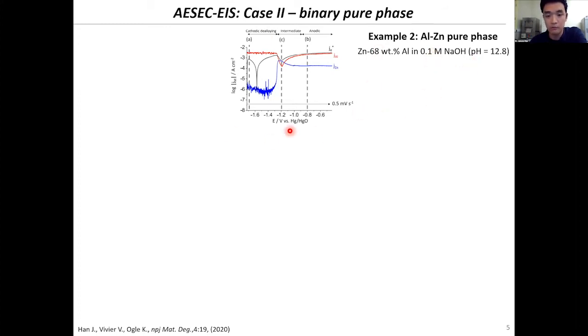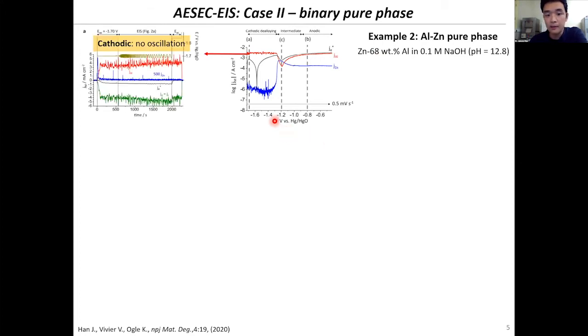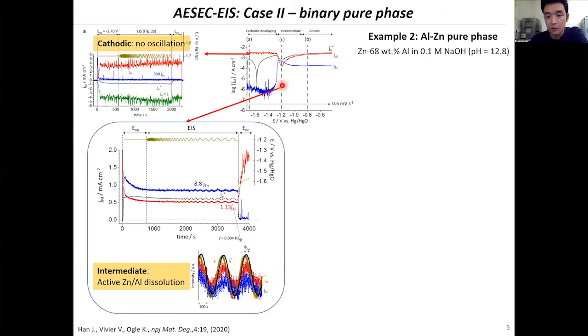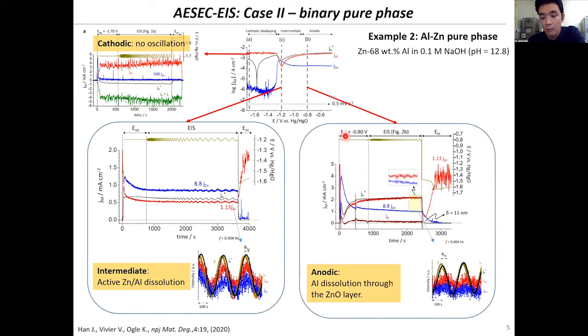So this is the polarization curve of this pure phase at pH near 13. And in the cathodic potential domain, when we apply a constant potential, we are not seeing any dissolution, neither aluminum nor zinc, which is in red and blue respectively. But if we increase to this intermediate potential domain, we start to see a nice oscillation correlating to the electrical current density. In this intermediate potential domain, we can say that zinc and aluminum both dissolve actively with charge transfer mechanism.